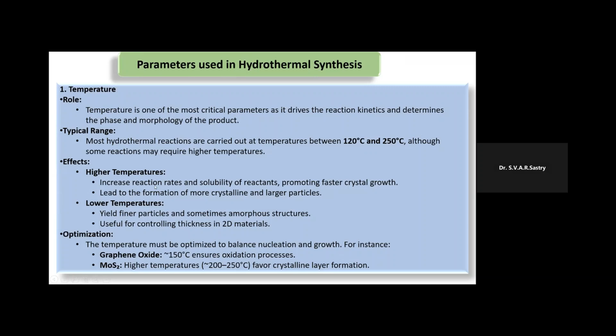higher temperatures. Higher temperatures increase the reaction rates and the solubility of reactants, promoting faster crystal growth in the autoclave. It also leads to the formation of more crystalline and larger particles. We see also that lower temperature in the autoclave gives finer particles and sometimes amorphous structures, useful for controlling the thickness in two-dimensional materials. So we observe that higher temperatures give crystalline materials by and large, and we get amorphous materials at lower temperatures. So we have to optimize.